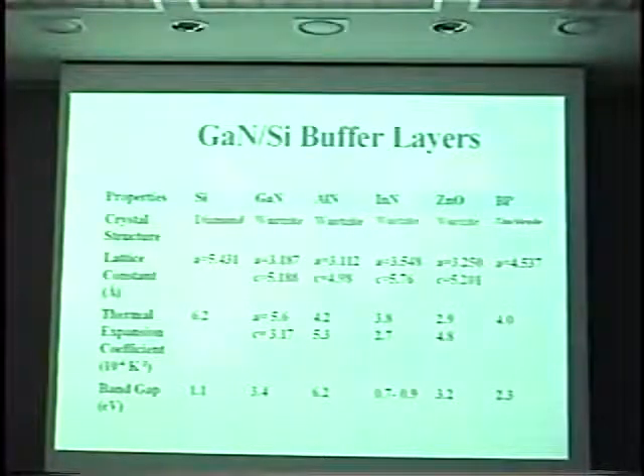Another approach is to intentionally put down a buffer layer that's better lattice matched, or perhaps softer, that can serve as a compliant interface. The candidates I'm going to talk about today are aluminum nitride, which has only a slightly smaller lattice parameter than gallium nitride, as well as zinc oxide, which is fairly closely lattice matched, a little over 2% mismatch, and boron phosphide, which no one has tried before. Boron phosphide is almost nearly lattice matched, and can also be grown epitaxially on silicon.